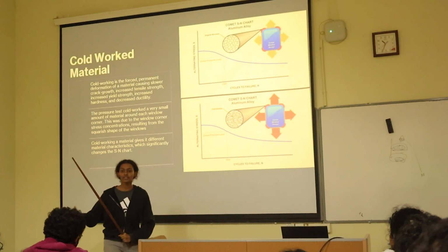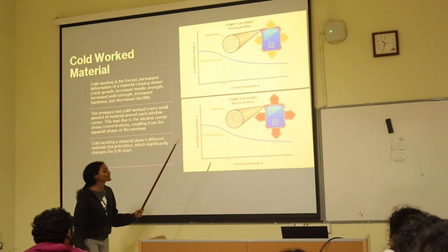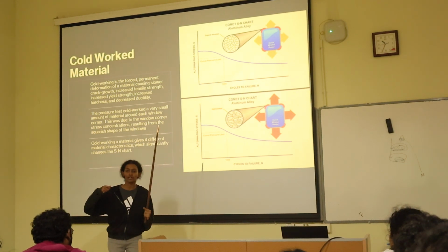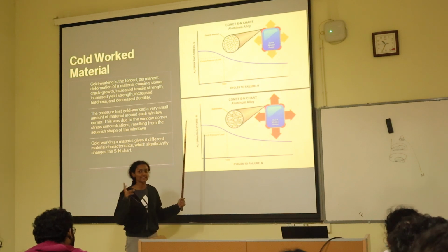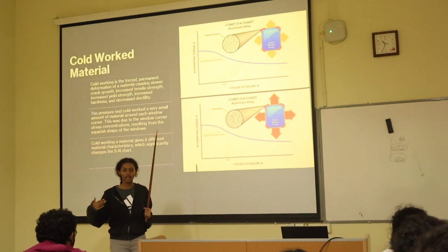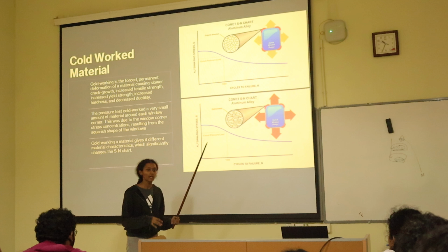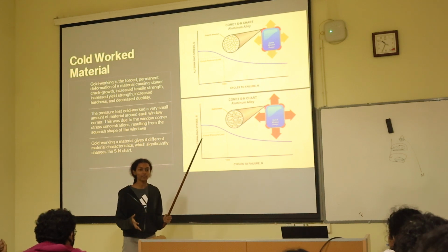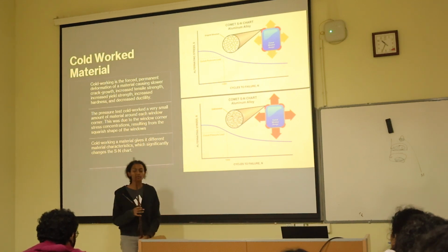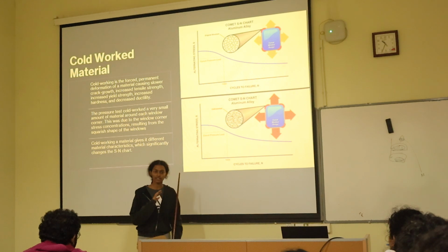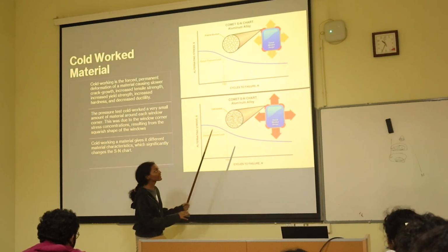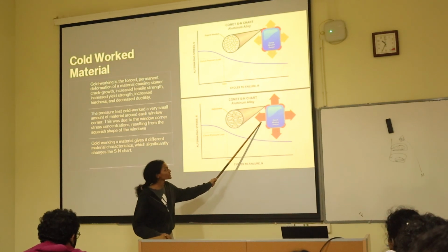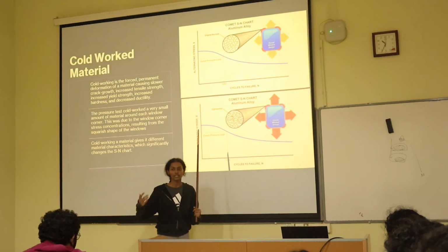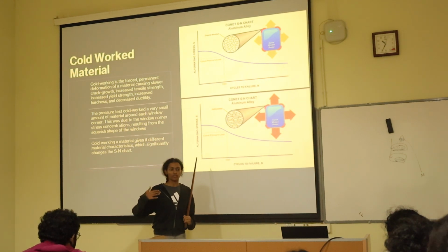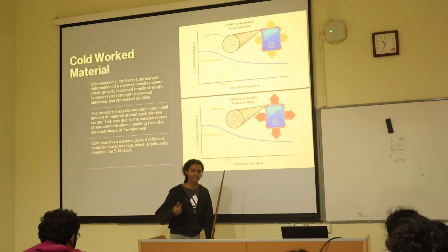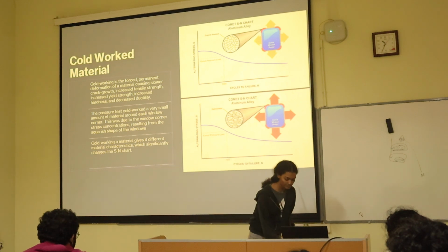When the fatigue test was done, the number of cycles which the pressure tested samples, the 2P pressure tested samples, could take was about 16,000 cycles. But the actual aircraft in the sky can only take P pressure. Those corners weren't cold worked, so they failed at a much lower number of cycles.